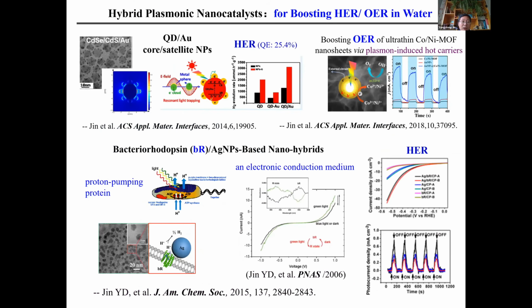We also prepare some hybrid nanocatalysts for HER or OER in water. For example, we prepared quantum dot gold core satellite nanoparticles and also bacteriorhodopsin gold silver nanoparticle-based nanohybrids, and use the plasmonic enhancement combined with the function of the protein to enhance HER.